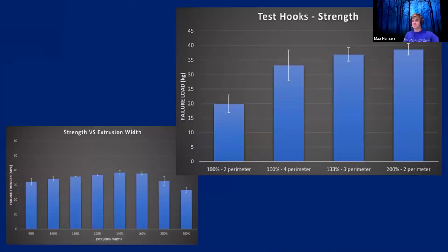And then going back to these hooks, you can see here with 100% extrusion diameter with 2 perimeters is down here. But then when you go up to 200%, it's all the way up here with a similar 2 perimeters. And I think it's very interesting to see this sort of increase when you increase the extrusion.